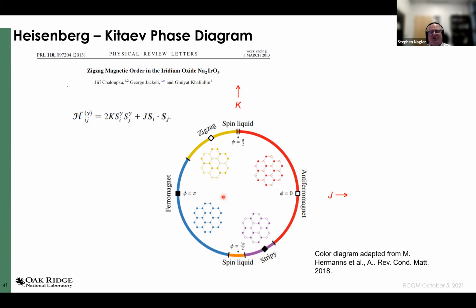One way to think of these is in the pure antiferromagnet, all of the nearest neighbors are oriented opposite to a given spin. In the zigzag model, 2 out of the 3 are actually oriented the same. The ferromagnetic model, they're all the same. And in the stripy model, 1 out of the 3 are oriented the same. Okay, those are the collinear models, the collinear spin structures you can have on a honeycomb lattice.